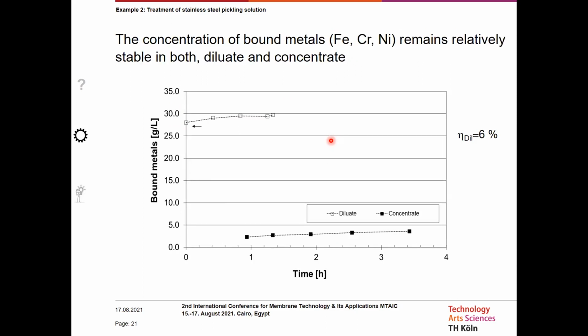Then we have a look at the metals. This combines the concentration of iron, chromium, and nickel in the solution. We can also see here that the metals are hardly transported through the membrane. So they remain in the initial solution. And this is what we wanted to achieve, to separate at least the nitric acid from the metal contents. The formed dilute contains more or less all the metals, and this can be used for further metal winning. And the concentrate solution with a high concentration of protons and nitrates can be fed back into the pickling zone of the